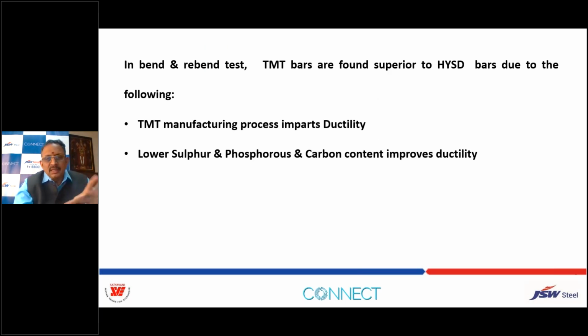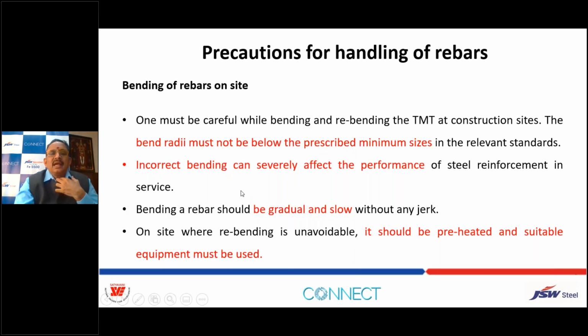Ductility is important in the TMT process itself, and low sulfur and phosphorus content improves the ductility also and fire resistance also. And bend radii must not be below the prescribed minimum sizes. So this is the very important point for bending of the rebar. That means when we detail, we should take care of this. And incorrect bending can severely affect the performance of steel.